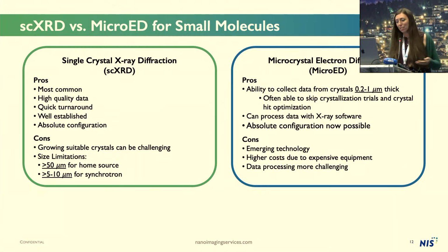So I've listed some size limitations here for X-ray. I'm sure that people will argue about these exact numbers, but there is a bottom size limit for these crystals, and the numbers I have here are generally for the smallest dimension of the crystal. So there is room for accessing structures from smaller crystals. MicroED, on the other hand, this is our big advantage, is that we can actually work with these smaller crystals. The ideal size of our crystals is less than a micron, maybe more than 200 nanometers in thickness, and then the other dimensions of the crystal can be larger for this technique. Generally, I prefer crystals that are a bit larger in the other dimensions, so that I have more copies of the unit cell and more intensity data. This allows a lot of groups to skip crystallization trials and optimization, and just move forward with their crystalline powder material, which is a great advantage.